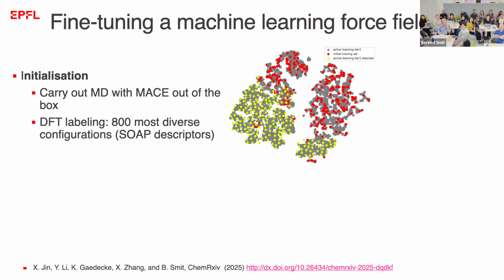Okay, so why is that important in the context of this fine-tuning? What you typically do with these force fields is you run a simulation. You do a molecular dynamics simulation, but that molecular dynamics simulation is done with a force field that is not sufficiently accurate. So you need to fine-tune. So what we typically do is you start a simulation, and that is this part of the red dots. Then we select, say, 800 most diverse configurations, for which we then do a DFT calculation. You add that to the training set, and you fine-tune.